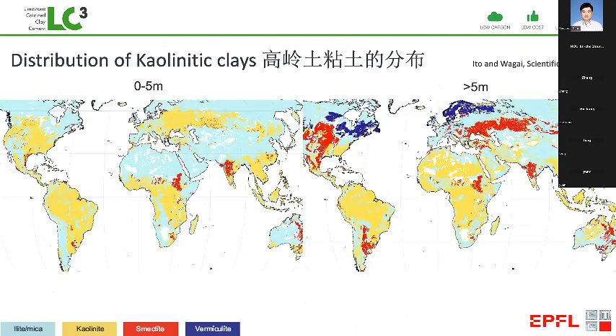This is the distribution of kaolinitic clays. Everywhere we see this orangey yellow color, we will have very suitable clays. And we can see in China that this, certainly in the southern part, is very, very abundant. And even in areas which do not look so promising, like for example in Egypt, where we have worked a lot, we have been able to find very good clays. So this color gives you a first indication, but there are also clays in many, many other places. This is very important.